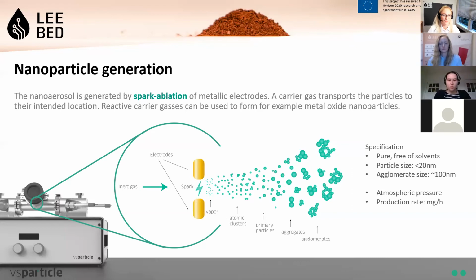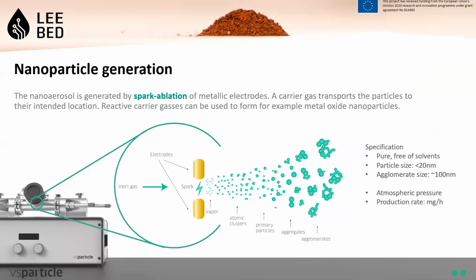So the nanoparticles are pure, solvent-free. The primary particle size is very small, sub 20 nanometer. The agglomeration size is larger, of course, it's about 100 nanometer. The entire process works at atmospheric pressure, and the production rate is about milligrams per hour. The actual number of the production rate depends on the material.